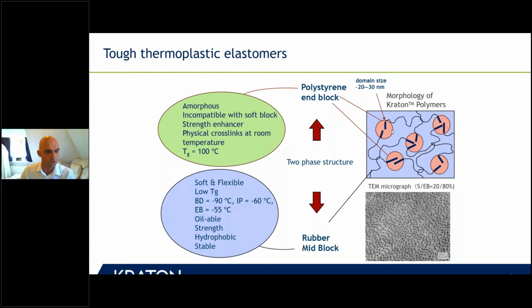And you have a physical cross-linking mechanism through the styrene blocks, which is driven by chemical incompatibility with the rubber, but also, of course, by a thermal effect of the styrenes having a much higher Tg, so they basically separate out also as a temperature effect. So they form amorphous domains, which give these physical crosslinks, which are of course reversible, because if you raise temperature, you take them apart at some point. And if you also put on shear, as you do in an extrusion process or in injection molding, you even take out more of that, and that is one of the key driving mechanisms in some of the situations where our polymers work so well.